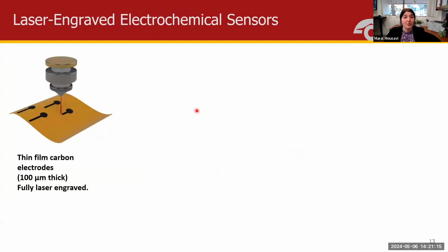Our fabrication for these electrochemical sensors is slightly different. We've moved towards carbon electrodes. These systems are fully laser engraved. We actually carbonize the material to form primarily graphitic carbon with high conductivity. So this is all engraved using a laser. The entire electrode has a thickness of about 100 micron.